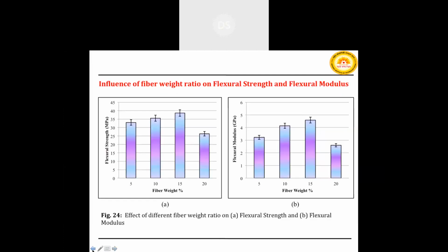The influence of fiber weight ratio on flexural strength and modulus. This figure indicates that the flexural strength and modulus increase with an increase in fiber weight ratio up to 15%. After that, again rising the fiber weight ratio decreases both the flexural strength and modulus because of poor wettability between Borassus fruit fiber and epoxy. The optimum value obtained for the flexural strength is 39 megapascal for 15% weight ratio of the fiber, which is 17% and 46% higher than the 5% and 20% weight ratio of fiber composite respectively.